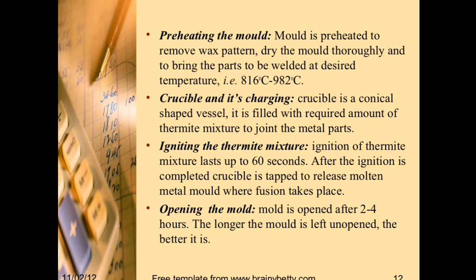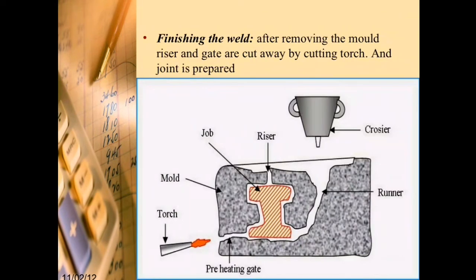Step 7, opening the mould — the mould is opened after 2 to 4 hours; the longer the mould is left unopened, the better it is. Step 8, finishing the weld — after removing the mould, the riser and gate are cut away by a cutting torch and the joint is prepared.